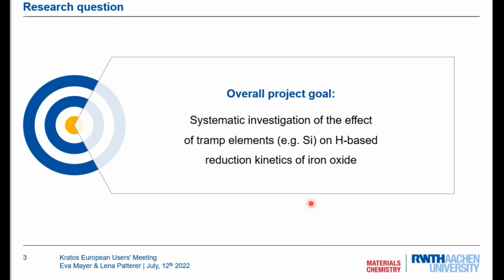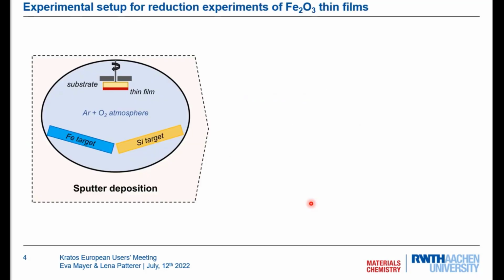So the overall project goal is that we want to systematically investigate the chemical effect of tramp elements, and today we want to present the effect of silicon on the hydrogen-based reduction kinetics of iron oxide. And how do we do that? So we don't use iron ores because they are quite complicated, and also when we want to look at it with XPS, it's quite surface sensitive. It becomes relatively complicated because iron ores also consist of pores and cracks, which makes it a little bit difficult.